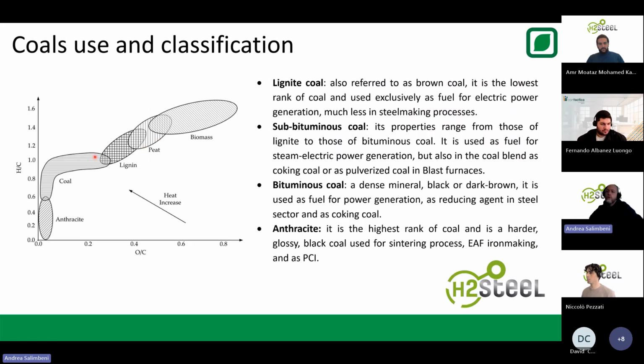So all these coals are used in the steel making process, but the coking coal and the anthracite are those really used. Anthracite is used mainly in the sintering process and as PCI. The coking coal is used both as a fuel and as a source of coke. Coke is produced where coal is pyrolyzed at 900 degrees to produce a particular high strength, low volatile material to be used in blast furnaces. So these are the coals that we need to replace if we want to decarbonize the steel sector.